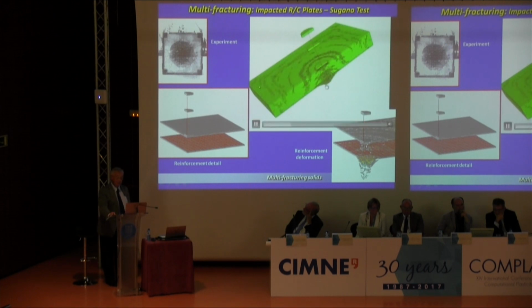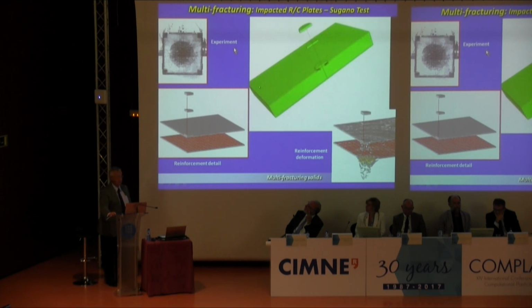And what you find is that, first of all, you get a compression wave that travels out, it's reflected as a tensile wave, and you have this spalling here. And then you also get a series of concentric rings forming here. And this is the deformation of the reinforcement at one stage of the process. Also, I should say, it looks complicated, but this is done on a normal desktop machine.